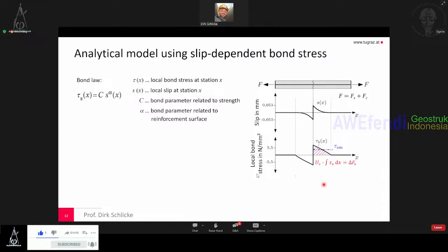The energy must be, of course, in equilibrium. So this means what we have below the surface of the curve of the bond stress, the area must be equal to the change of the force in the steel bar. And from this, we can obtain now the steel stress distribution. The steel stress at the crack is the largest, and that decreases, decreases, decreases due to the bond stiffness. And when the slip is zero, of course, the steel strain and the concrete strain are equal to each other.